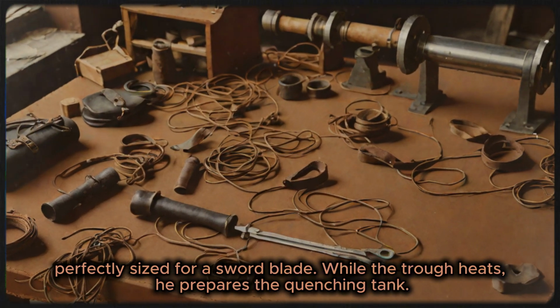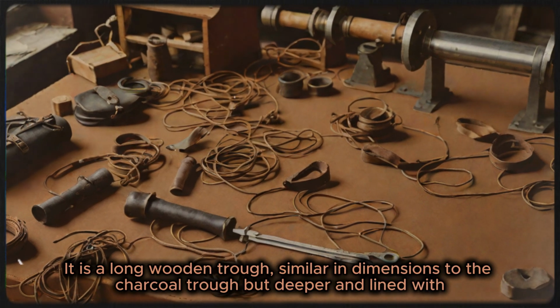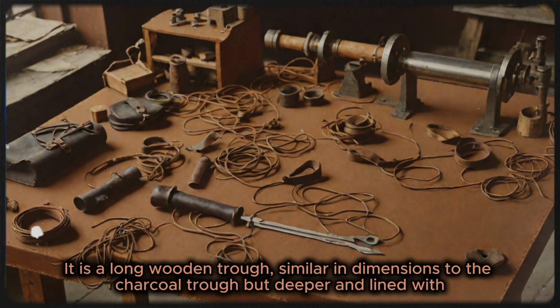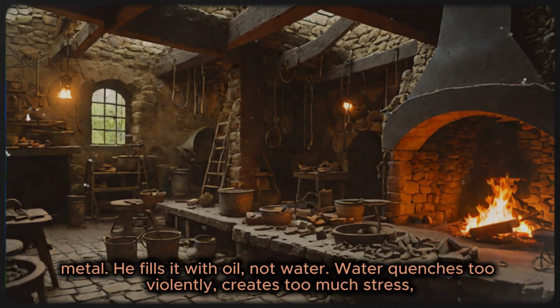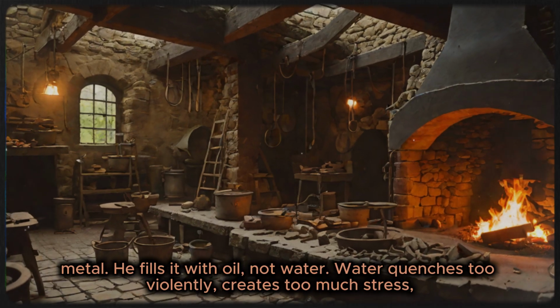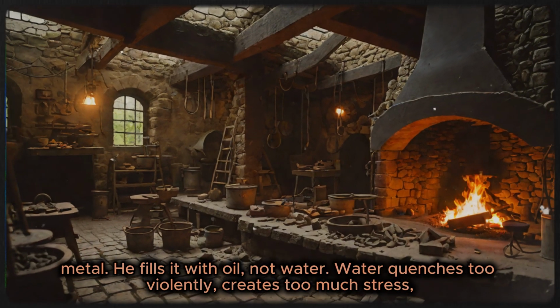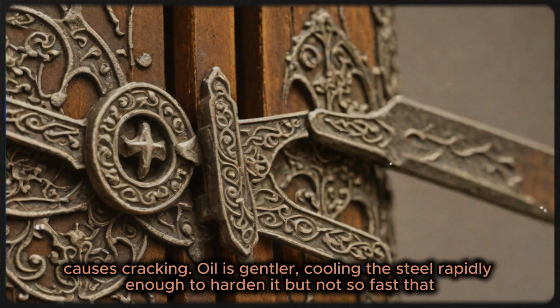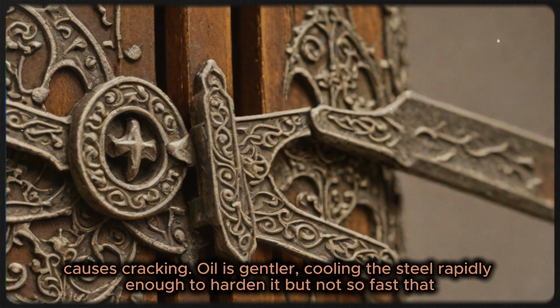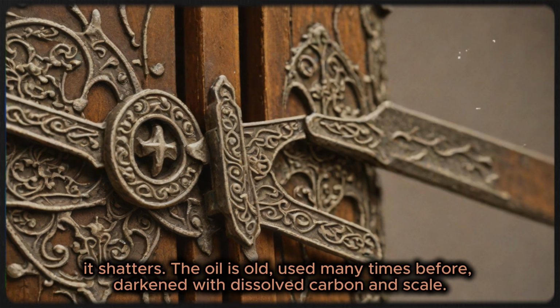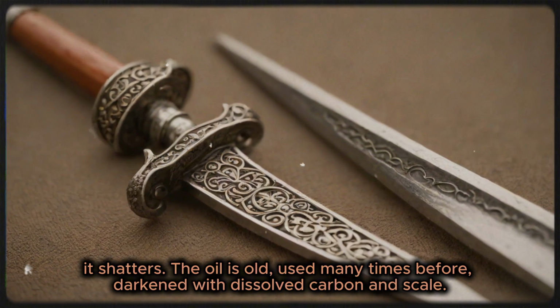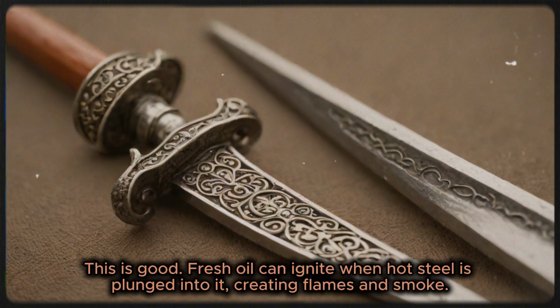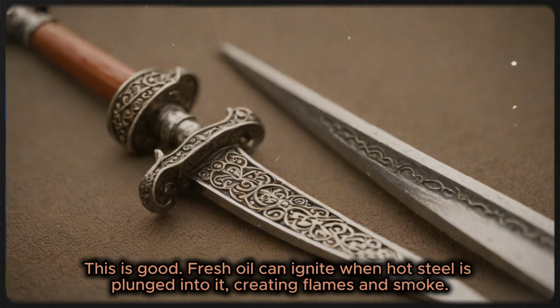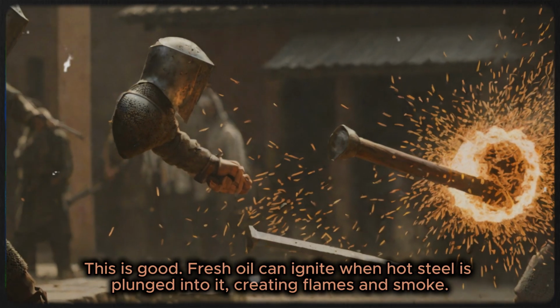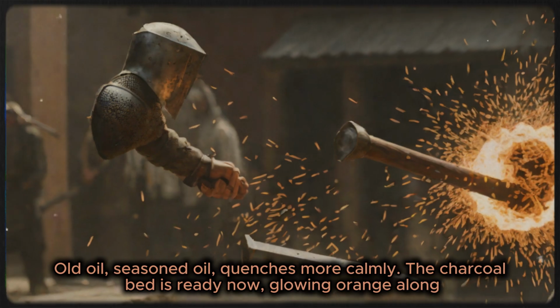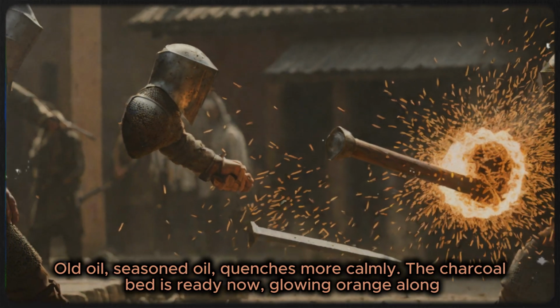While the trough heats, he prepares the quenching tank. It is a long wooden trough, similar in dimensions to the charcoal trough but deeper and lined with metal. He fills it with oil, not water. Water quenches too violently, creates too much stress, causes cracking. Oil is gentler, cooling the steel rapidly enough to harden it, but not so fast that it shatters. The oil is old, used many times before, darkened with dissolved carbon and scale. This is good. Fresh oil can ignite when hot steel is plunged into it, creating flames and smoke. Old oil, seasoned oil, quenches more calmly.